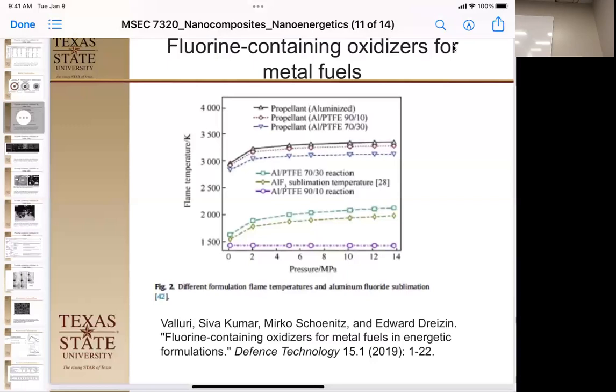And so if we look at our different systems here where we have a propellant, the propellant here uses aluminum metal as the fuel, okay? And in the case of when we burn it in oxygen, you get aluminum oxide, which is very abrasive and comes out from your system. Well, in this case, when you use aluminum with Teflon as the oxidizer, instead of an oxygen-based system like ammonium nitrate or something like that, which would be in a different propellant, we can actually look and see that the top one is an aluminized propellant with a polybutadiene binder and ammonium nitrate as the